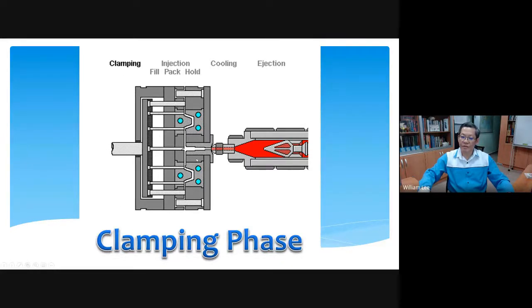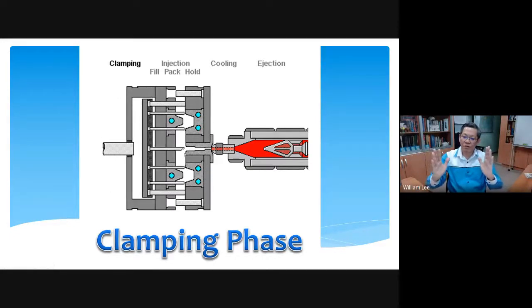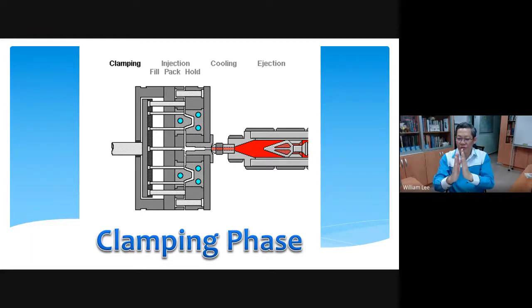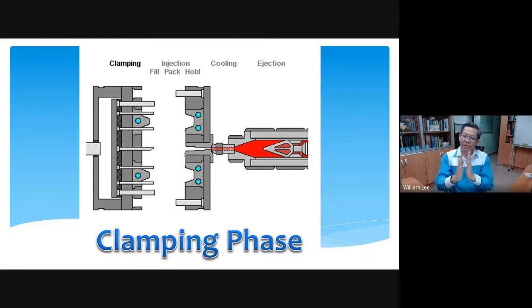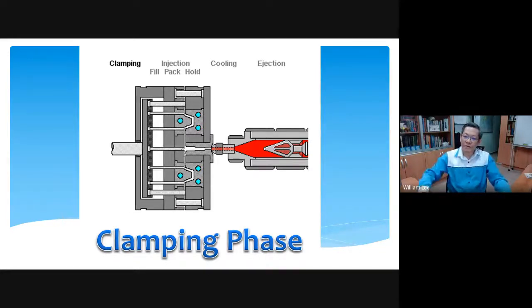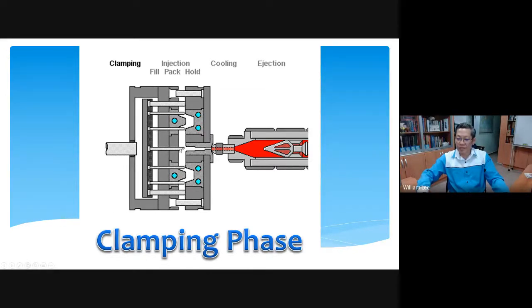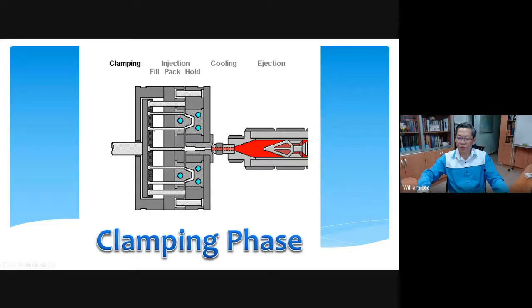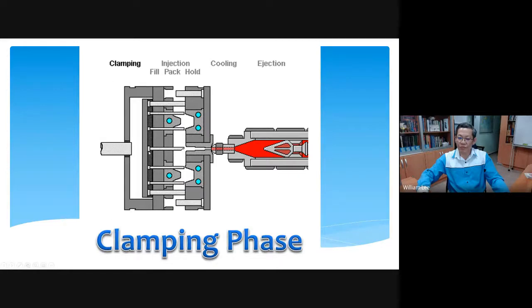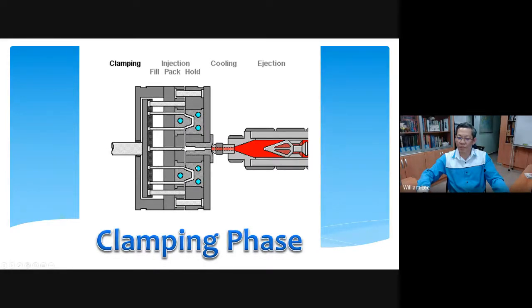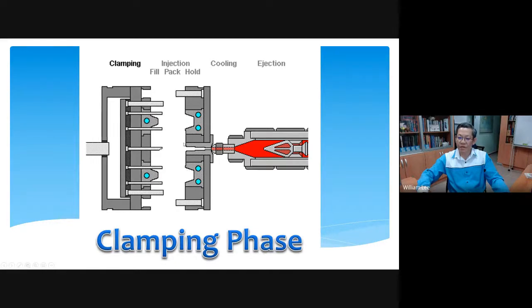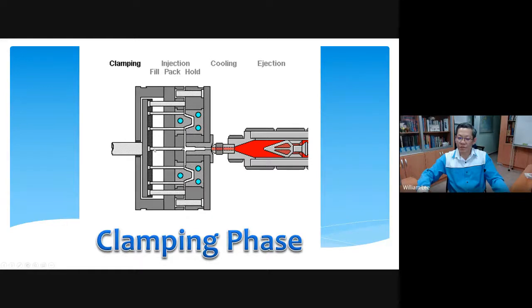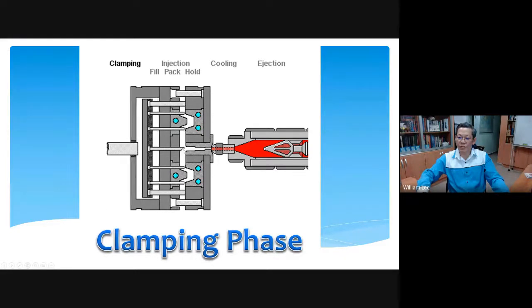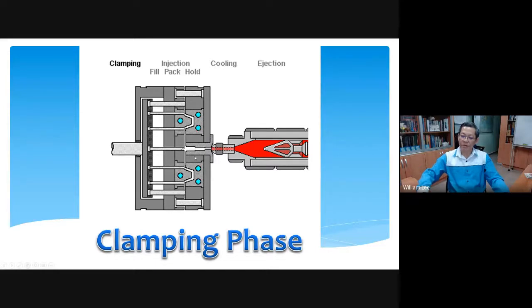So during the clamping, these two mold halves need to come initially at a fast speed, right? Then when they come to a closer distance, they have to slow down to avoid slamming onto the other half, and then you damage your mold. But I can see there is some imperfection from the simulation. As you can see, why? Because this ejector pin is supposed to retract back to the original position, but not project out. So I think this is an error from the simulation program here. Otherwise, when the other half is getting close to this A half side, this projected pin might crack when they hit this half here. But anyway, this is the clamping phase.